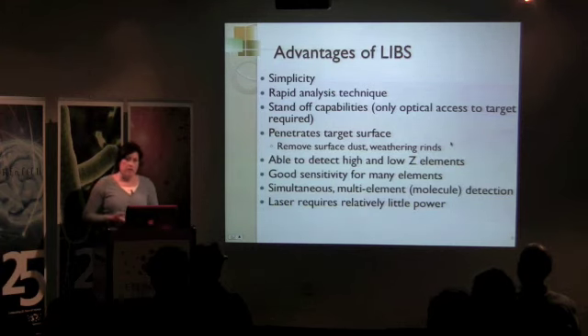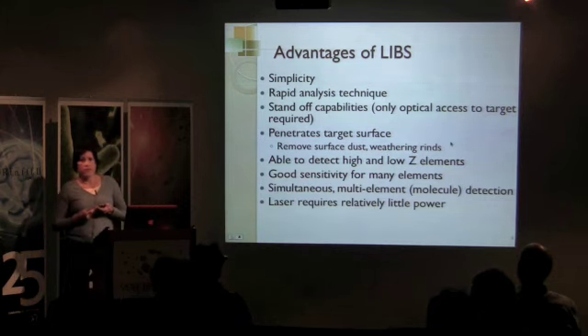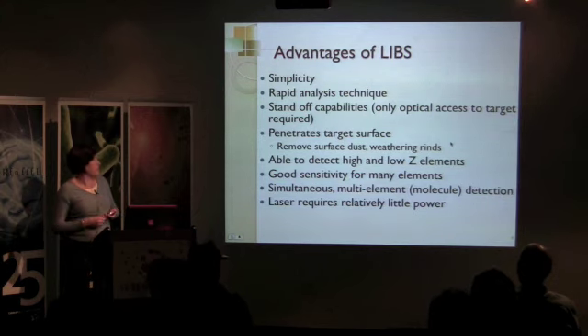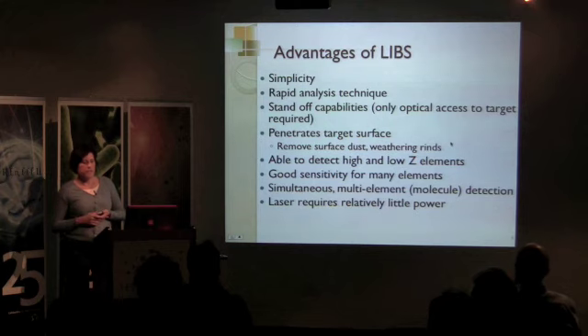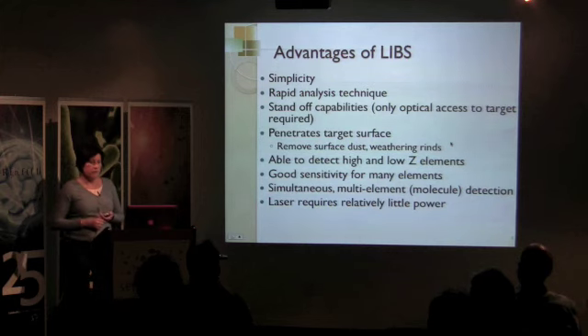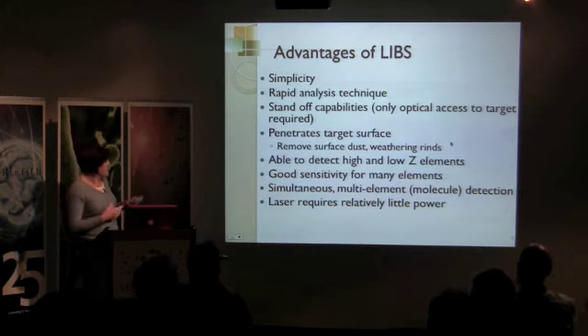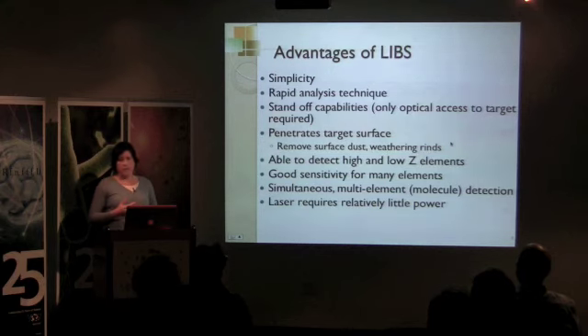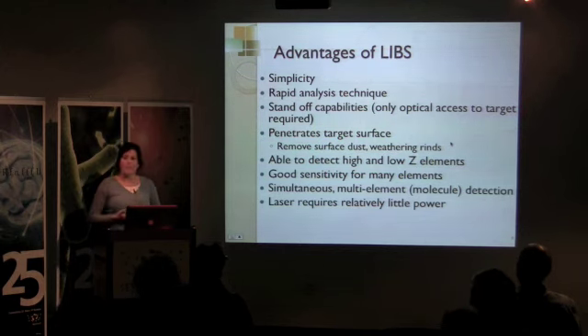It's also able to penetrate target surfaces very, very shallowly, but if there are any problems with surface contamination or residues or dust, this offers a way to remove those to get at the innate sample. This technique gives you a capability to detect a whole range of elements simultaneously, both high and low Z, and has very good sensitivities for many of these elements down to the ppm level. And finally, the laser technology requires relatively little power these days, and so this technique lends itself to portability and also to small payloads on planetary rovers.